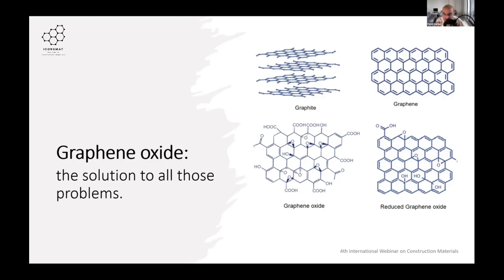From the comparison between the molecular structures of graphene and graphene oxide, as you can see, it yields a relatively lower thermal and electrical conductivity than pure graphene because of the impurities embedded in its structure, which is both good and bad. It appears to be good for a lower corrosion rate and bad for the conductivity matters. Nevertheless, the major advantage of reinforcing concrete with graphene oxide and not graphene is the affordability of this material, because after reviewing the literature, there has been no significant difference observed between these two in terms of mechanical performance in concrete. So basically, by using graphene oxide instead of graphene, you can save a lot and get the same outcomes from the mechanical perspective.